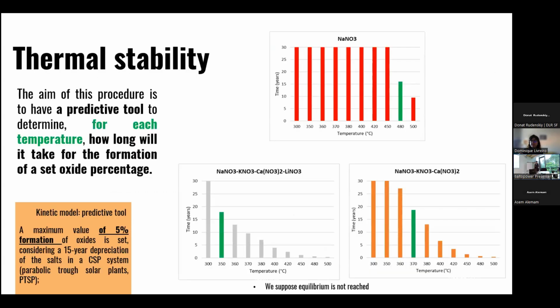Just as a comparison, we did some calculation to have a predictive tool to determine for each temperature how long it will take for the formation of a set oxide percentage. Here I reported a maximum value of 5% formation of oxides, considering a 15 years depreciation of a CSP system. As you can see, there is the comparison between sodium nitrate and a quaternary mixture containing calcium and lithium and a ternary mixture containing calcium. The green line represents the temperature at which you have to use the salt to reach the maximum formation of the oxide in 15 years. It's quite different in the three scenarios.